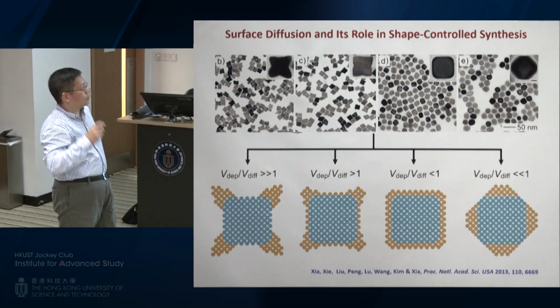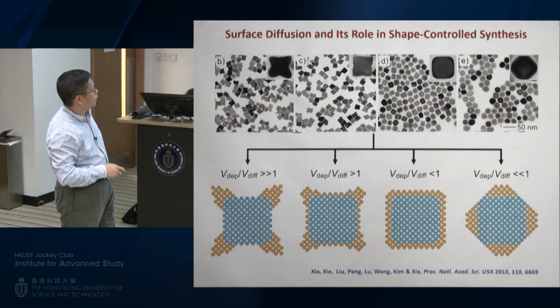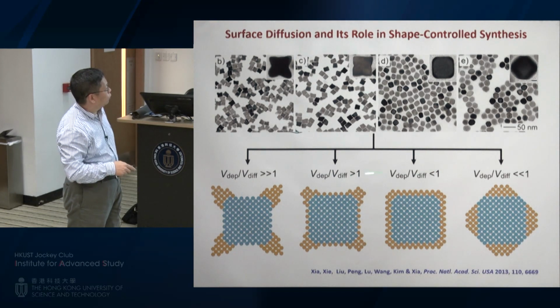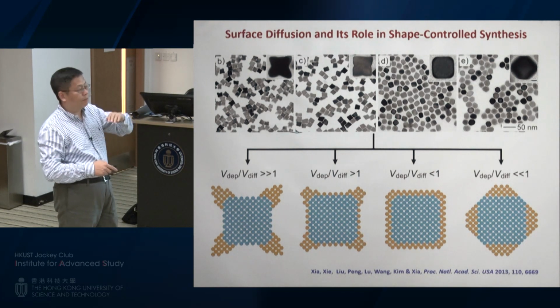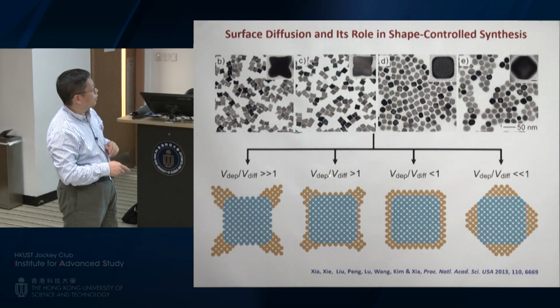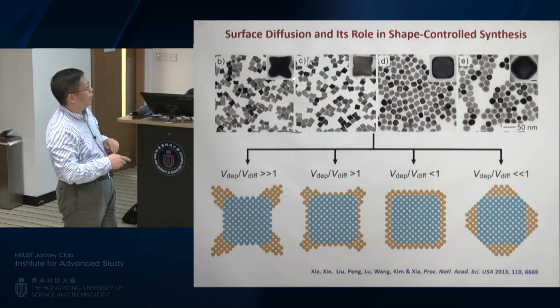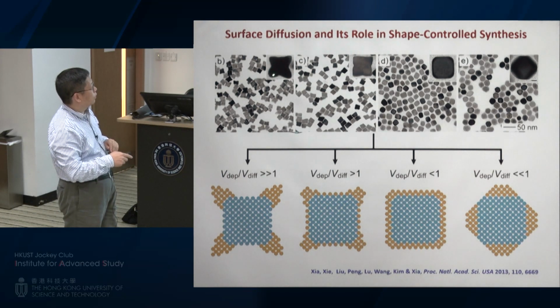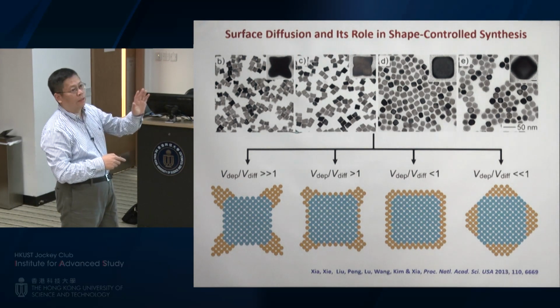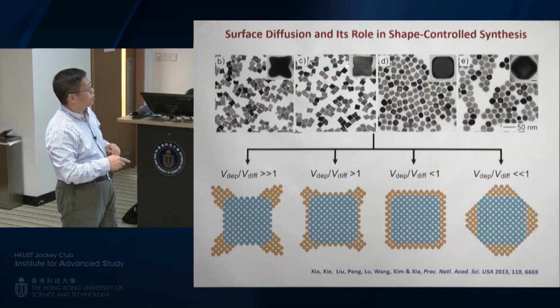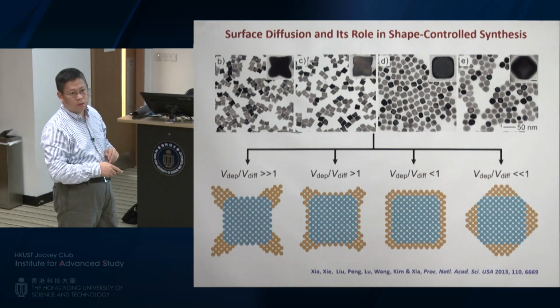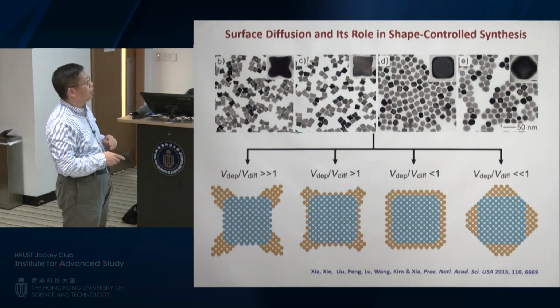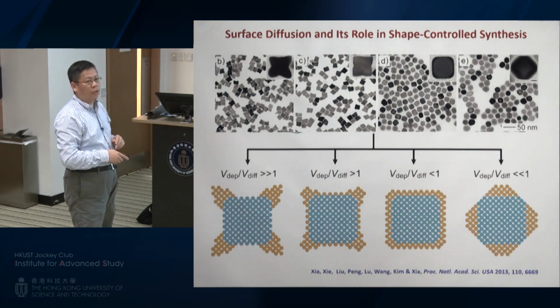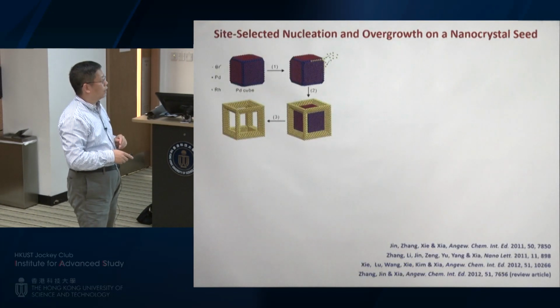In another set of experiments, if you look at this paper, you can see that we can fix the diffusion rate. You use the same temperature, but you can change the deposition rate. You are going to observe essentially a similar trend. If you have a very high deposition rate, you're going to have octopods, and then that will basically change as the deposition rate becomes slower and slower. So it's a pretty unique control by controlling the kinetics.